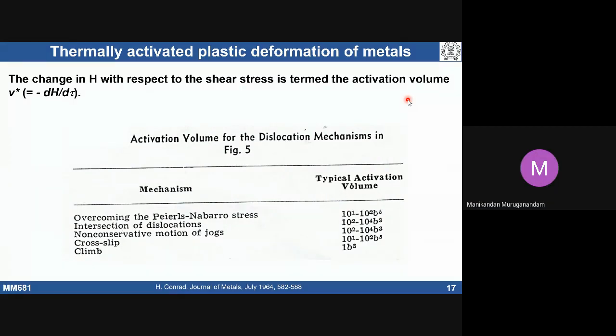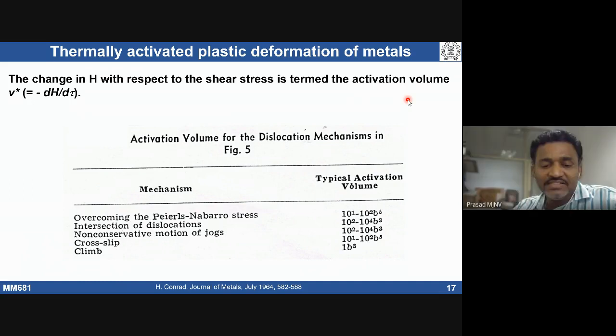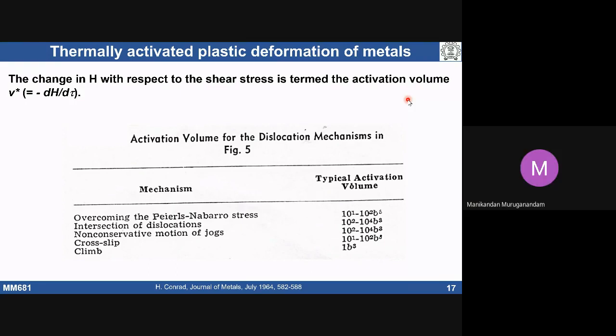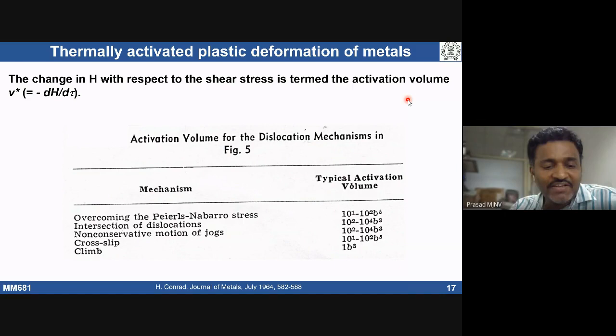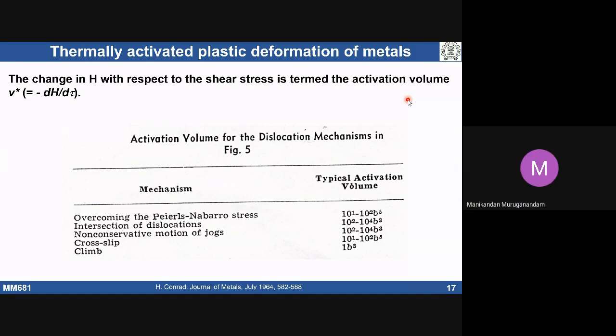Yes, sir. Can we call the grain boundary also a thermal barrier? Because with increase in temperature, the mobility of the grain boundary also increases. See, the grain boundary is fine if it is small, within that 10 atomic diameters. Typically we say 0.5 to 1 nanometer. If I take a material whose atomic size is, assume, 3 angstroms, how many atoms do you have across the boundary?